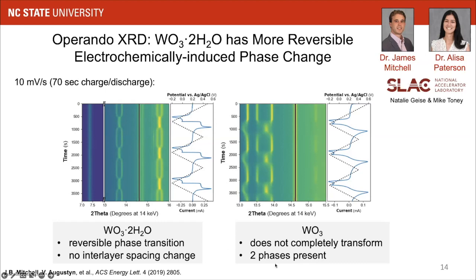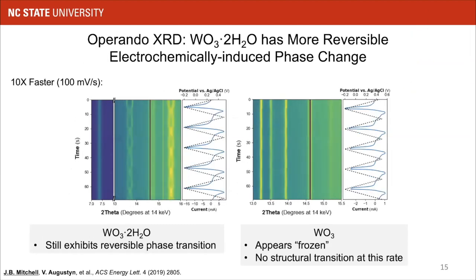On the other hand, for the anhydrous tungsten oxide, which can also accommodate protons, we see a very sluggish phase transition process. The material never fully transforms to its next structure. The two phases are always present. And when we push it to operate at an even faster rate, we see that the hydrous material is able to keep up with the phase transition, whereas for the anhydrous tungsten oxide, the diffraction peaks appear almost static, frozen, and there's no structural transition at this rate.